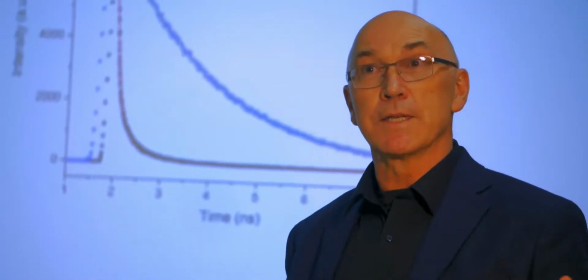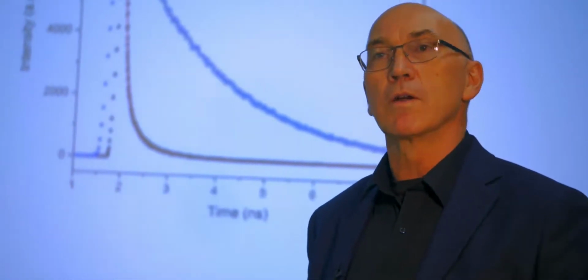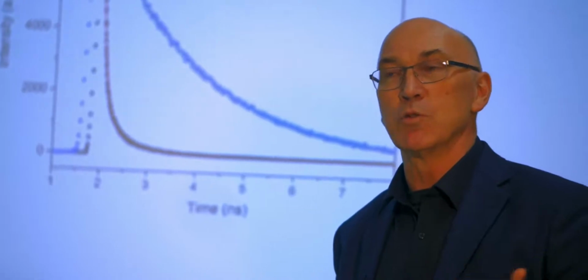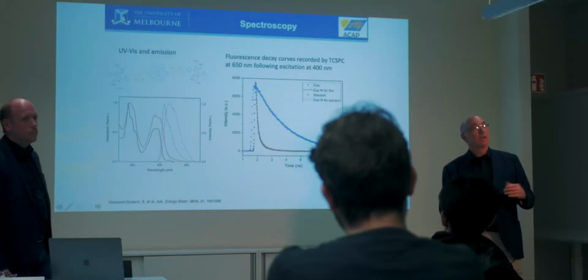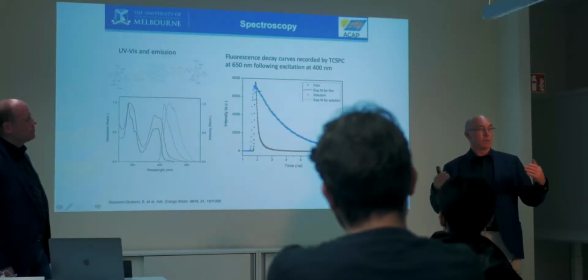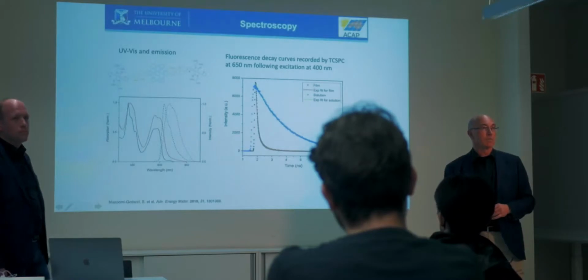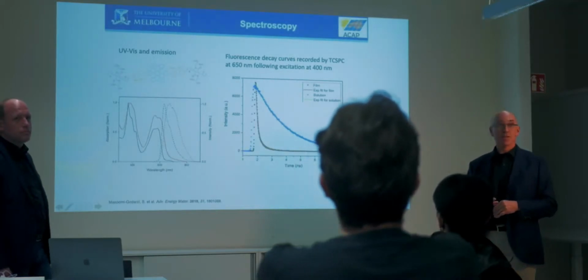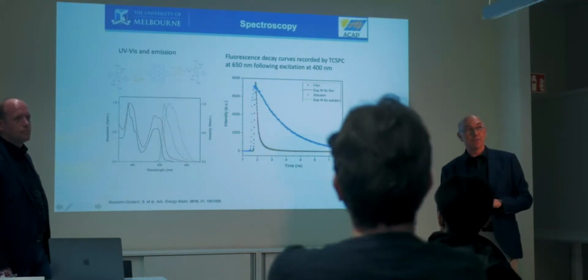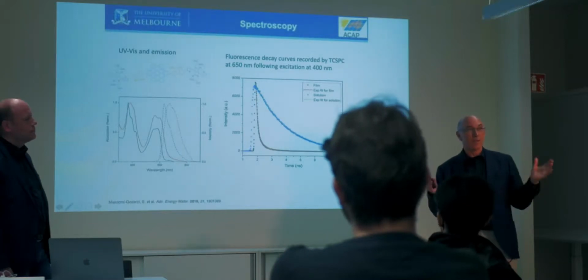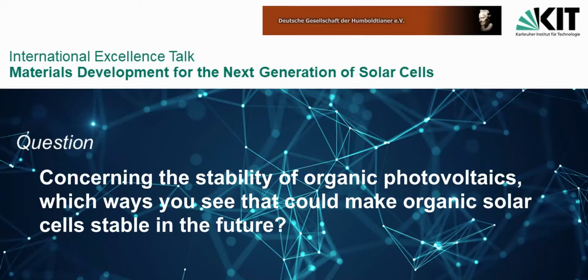So these are all air stable. They may interact with oxygen, but they don't get oxidized by oxygen. And so we don't really want something which is so air sensitive that we can't use it. So we're looking for chromophores that are inherently stable. There are a lot in the literature, and we're using those, and we're also designing our own chromophores. Yep. So all of our current materials are all worked up on the bench in air, and they're all stable.